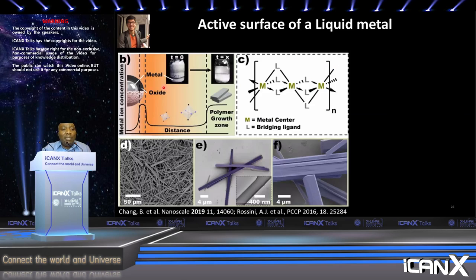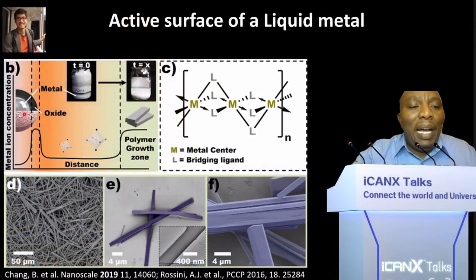And with this, Boyce Chang, who is now at Berkeley, did beautiful work building this story, where the balance between the etch rate and the growth was controlled by the thermodynamics of mixing and solubility, delta G_M, in the solvent that we chose to use. We can set up this reaction and wait for months, and the crystals will grow so long that you can actually pick one of them and see it by eye.